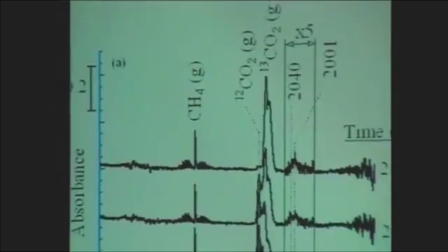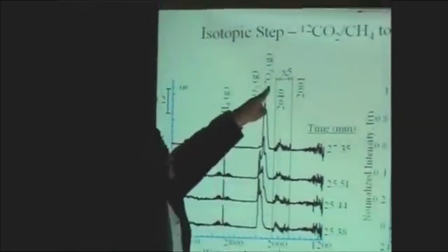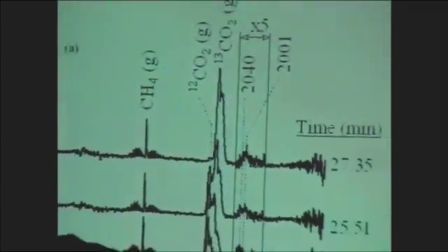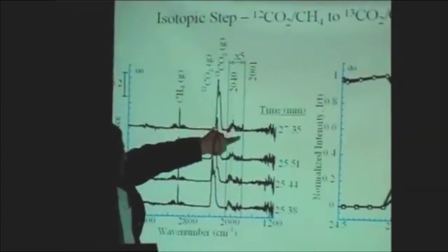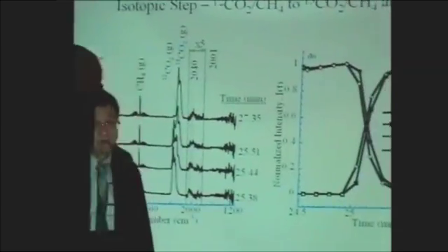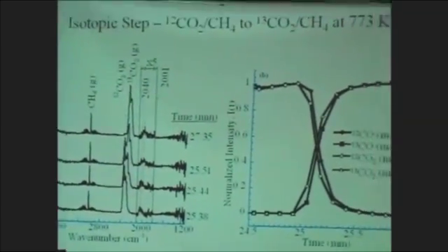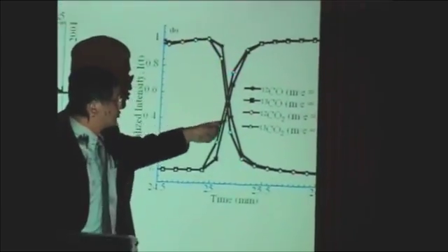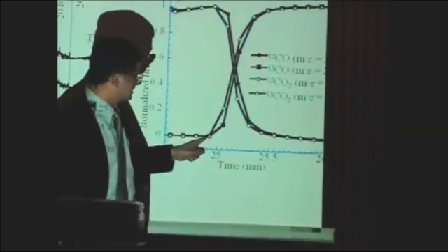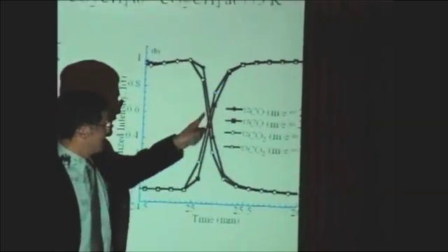We also use the isotopic tracing technique here, by switching from one species, for example 12CO2, to 13CO2, to determine how fast the switching takes place and how long this adsorbed CO stays on the catalyst surface. This is not a very good result, but we can see there's a switch from linear 12CO to 13CO, and we can compare the response. We can see the 12CO2 is coming down, and 12CO is coming down, and 13CO2 is going up, and 13CO is coming out.